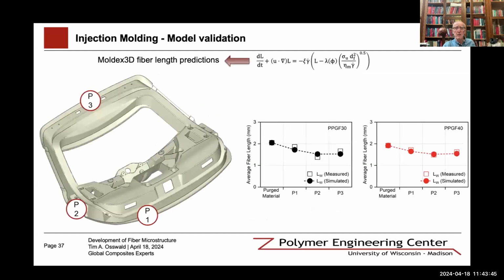That was then implemented together with our friends at SABIC and the people at Moldex3D for this trunk lid, a demonstrated trunk lid that SABIC has. And it's more complex. There are several gates there where you control when each gate is opened up during the process, but you can see in positions 1, 2, and 3, we can actually predict quite well the fiber length distribution. Again, here we have as an input the fiber length distribution of the purged material from the plasticating unit. But once we have that, we can actually predict quite well what happens during the process.